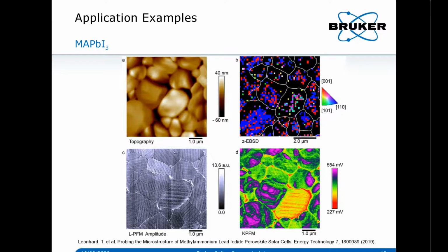experiment observation, how to understand this kind of materials. Actually, if you combine this kind of observation with EBSD, you will see that the crystal orientation of this grain is also different from the rest of the grains. So if you combine these things together, you can have a full picture of how this kind of piezoelectric domains distribute in specific grains, and how different grains may have different nanoelectric properties over the whole material. So this is just a very nice example to show you how to combine all different modes of AFM, and also together with other technology to fully understand the material behaviors.